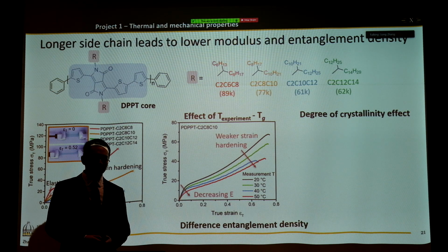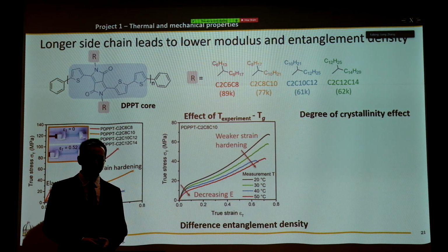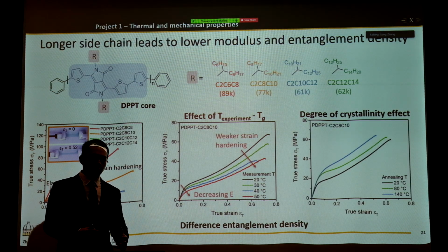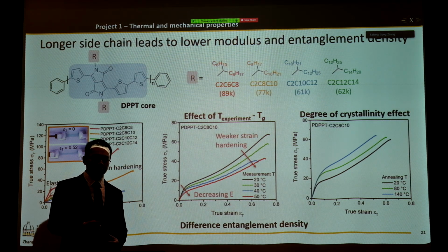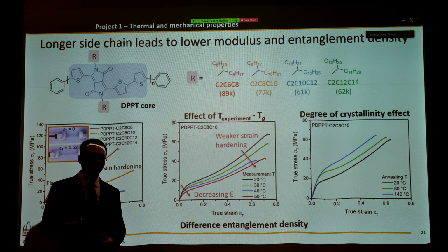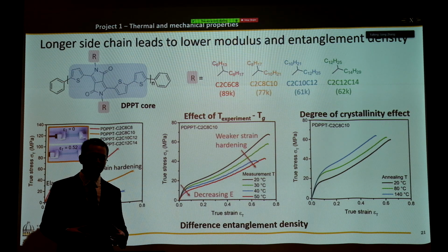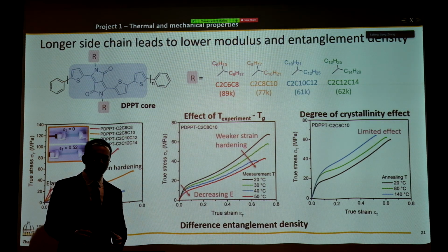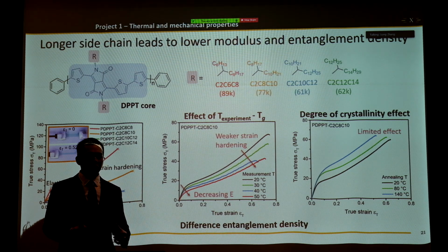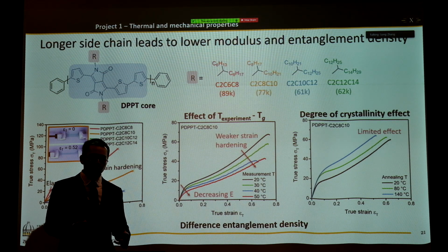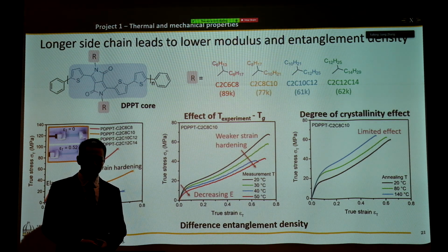So let's take a look at the degree of crystallinity effect. We can change the degree of crystallinity by thermal annealing the material at different temperatures and for different times to allow the crystalline domains to become larger and larger. And we find that strain hardening was not significantly affected by the degree of crystallinity. This observation agrees with previous studies on traditional polymers.